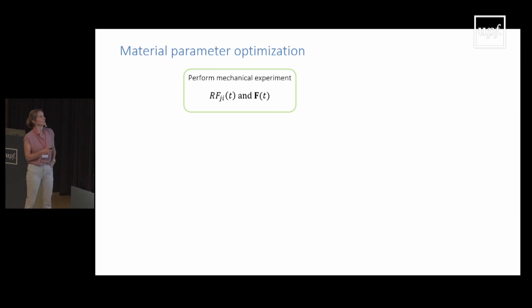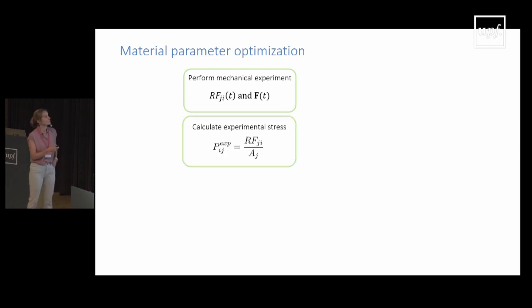So you perform your mechanical experiment, which means that you can measure some forces in different directions, and you can measure a deformation gradient using a camera. You can then, with that information, calculate experimental values for your stress. So stress is force divided by surface area.